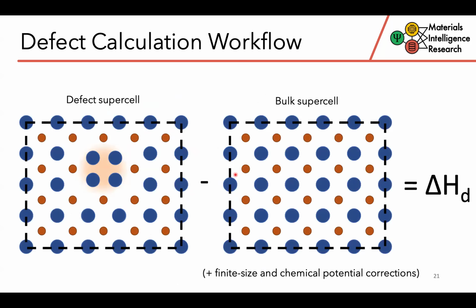and from that compute the formation energy. And so to compute the formation energy is very simple. We just take the energy difference of our defective supercell compared to that of the bulk or pristine defect-free supercell. We do have some additional corrections to add in here, such as finite size charge corrections to account for any long range charge effects from a defect, and also chemical potential corrections to account for the fact that we've added or removed atoms to create this defect.